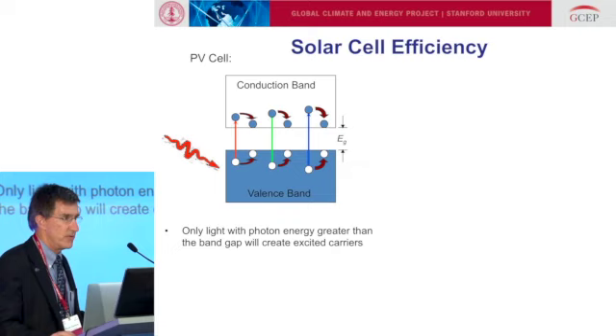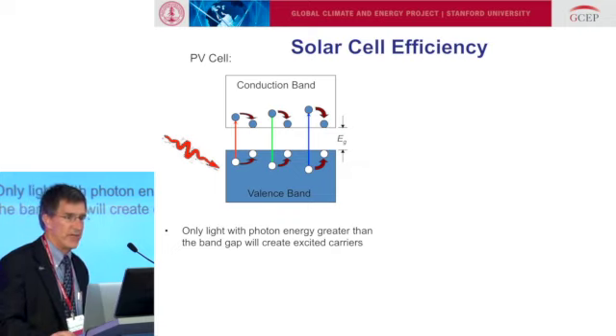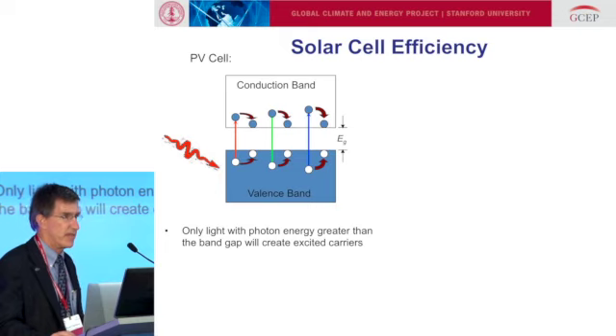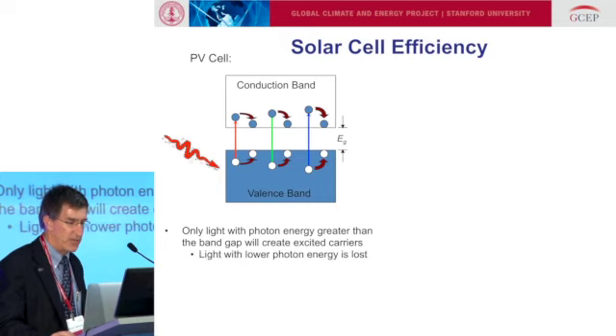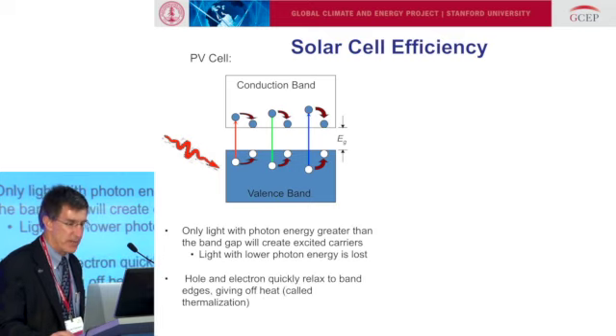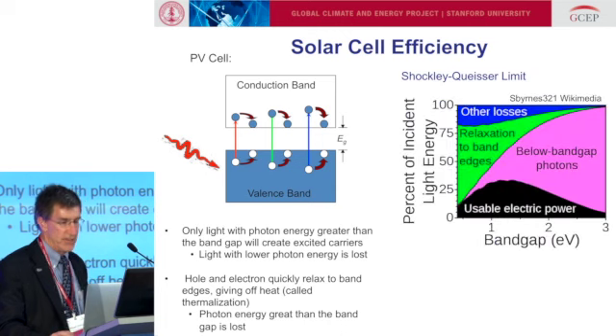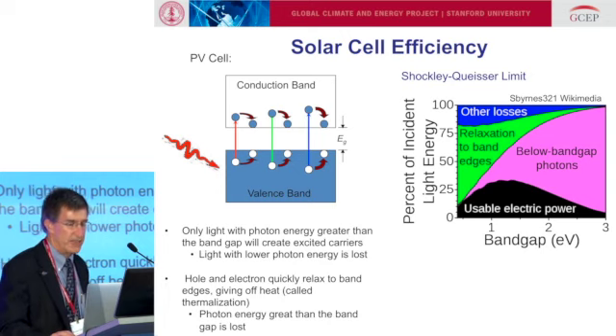You also lose all the photons which don't have enough energy to excite an electron from the valence band to the conduction band. So those are two big losses in a solar cell, and that greatly limits the efficiency you can get. People looked at this some time ago. Shockley and Queisser is a famous paper, and they calculated, using a detailed thermodynamic balance, what efficiency you can get from a single junction solar cell.